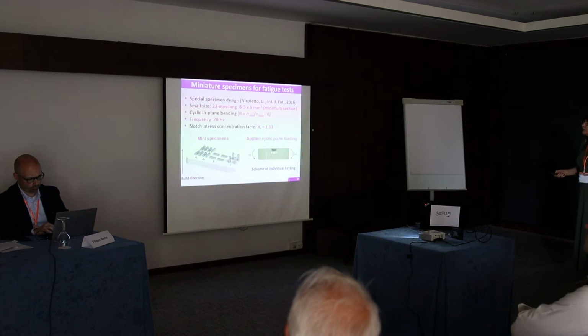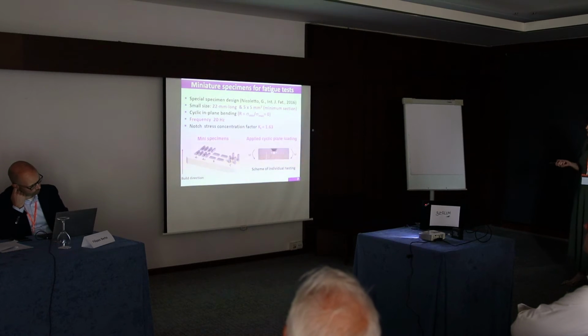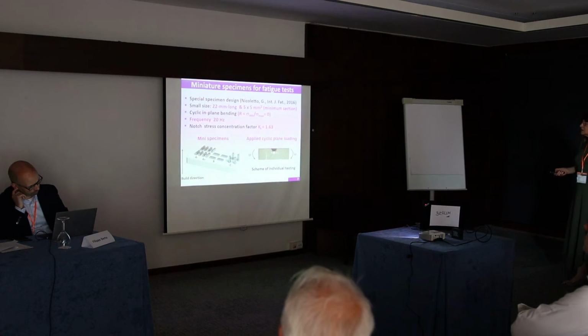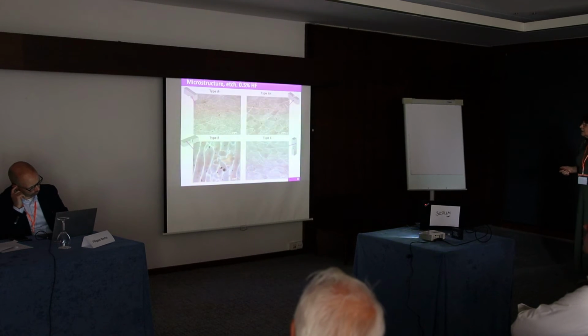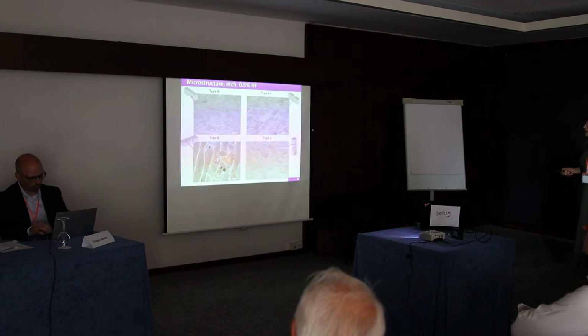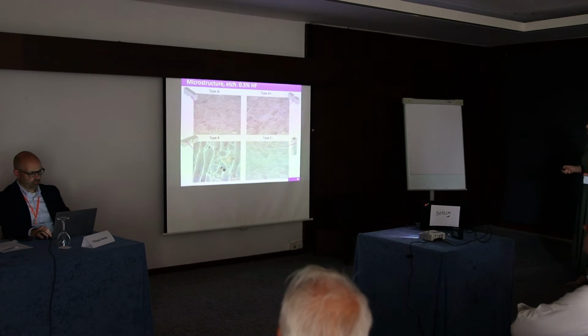Here we can see mini specimens for orientations A minus, A plus, B and C, and the applied cyclic bending is shown in this picture. This is the scheme of individual testing. Here we can see the microstructure corresponding to each orientation. Types A minus, A plus, and also type C are similar because they are vertical. For orientation of specimen B, this is the microstructure, as we can see on this slide.